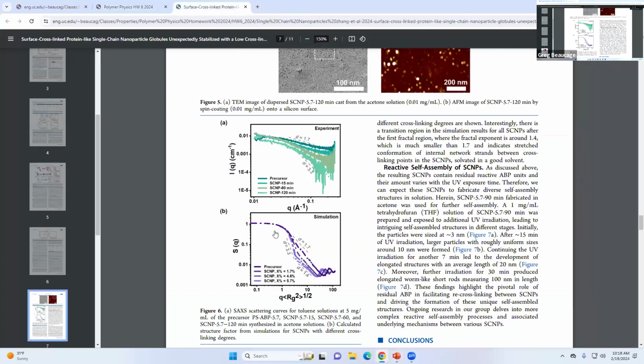So he says 1.7 is actually too steep, right? 1.67 would fit this thing perfectly. That's the odd thing. If you numerically integrate it, you get 1.72. And if you do computer simulations, they get 1.7, which is 1 over 0.588, so you see the 0.588. But the data, when you measure it, is always like 5/3, which it shouldn't be. But I'll show you later on, maybe today, how Grosberg can get that 5/3 without the assumption that you have to drop off this third term.